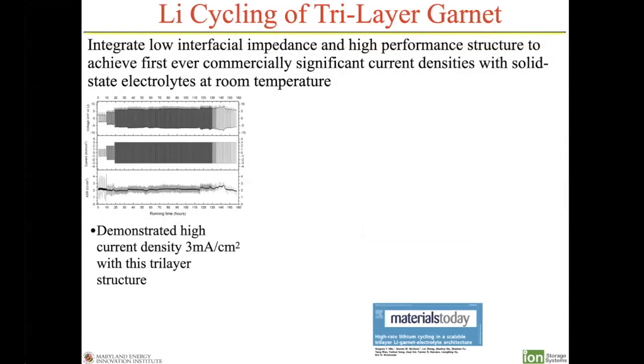So now combining these two things, that three-dimensional structure with the surface coating, we're able to go to quite high current densities. The data on the left is at current densities of 1, 2, and 3 milliamps per square centimeter. The data on top is the corresponding voltage, and at the bottom is the ASR of that cell.